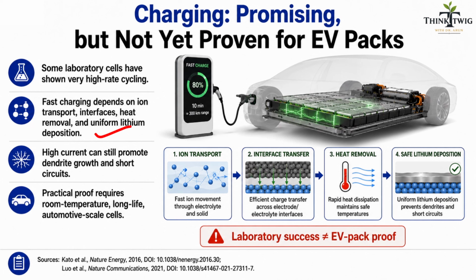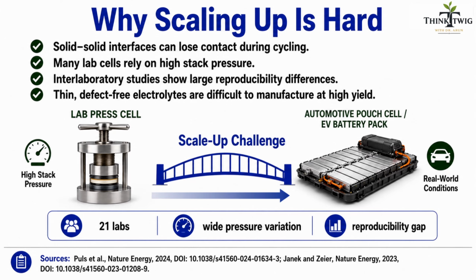Fast charging is not only about ion speed. The ions must cross the interfaces. They must move through the cathode. Heat must escape, and lithium must deposit evenly. If it deposits unevenly, sharp structures can grow. They are called dendrites. Luo and colleagues observed such structures in sulfide cells. They moved through the electrolyte and eventually caused short circuits. So the 3-minute result is important and it proves scientific possibility. But it does not prove a 3-minute EV charge at room temperature. Not yet.